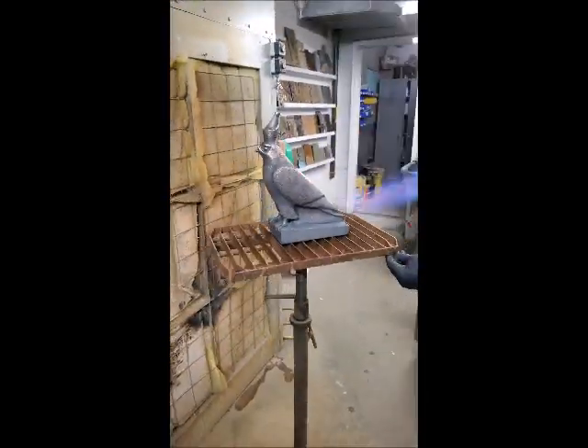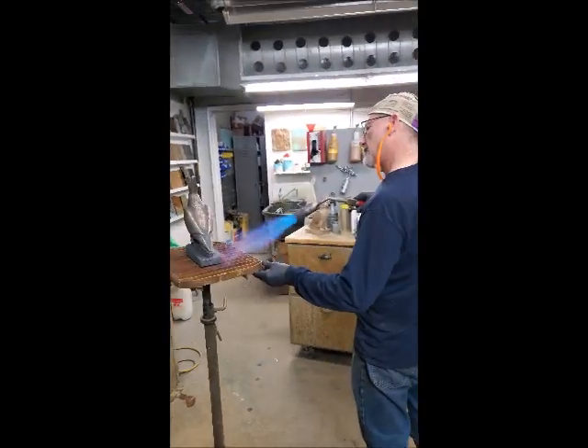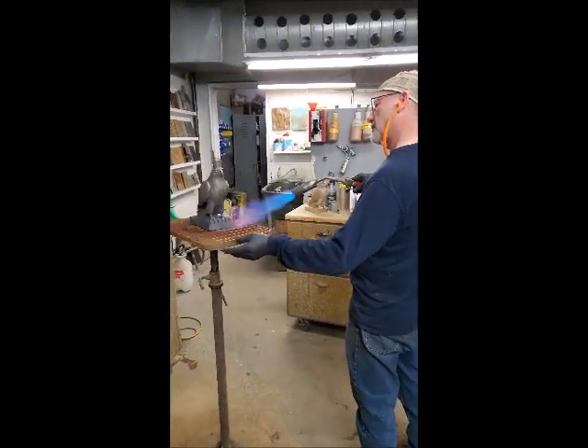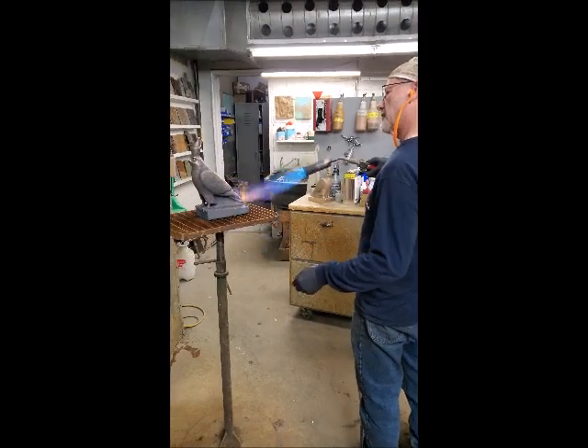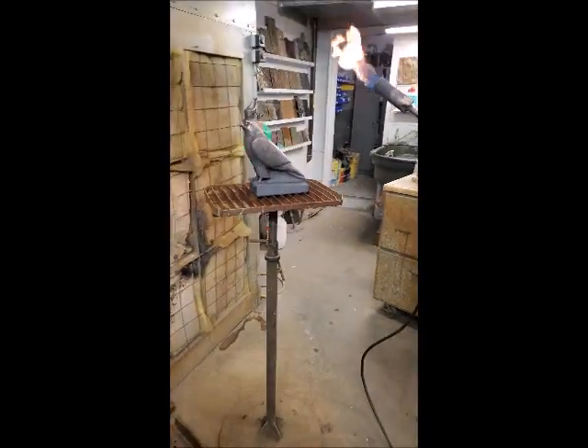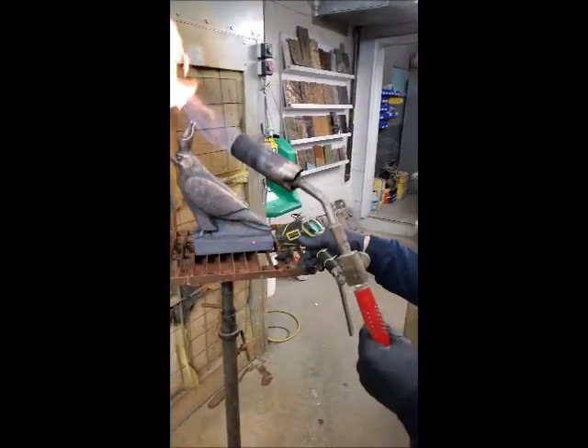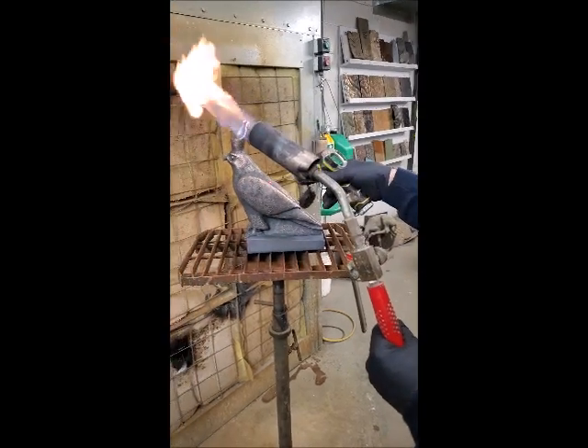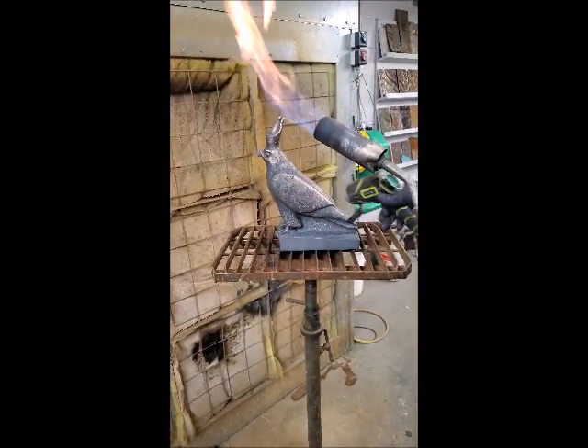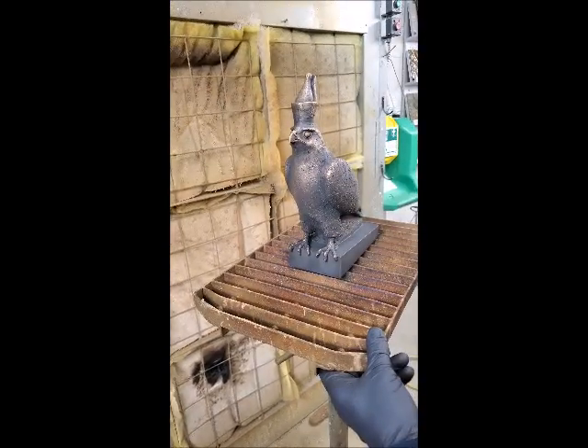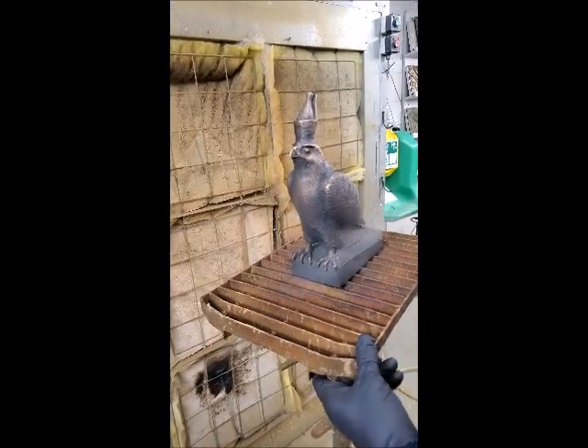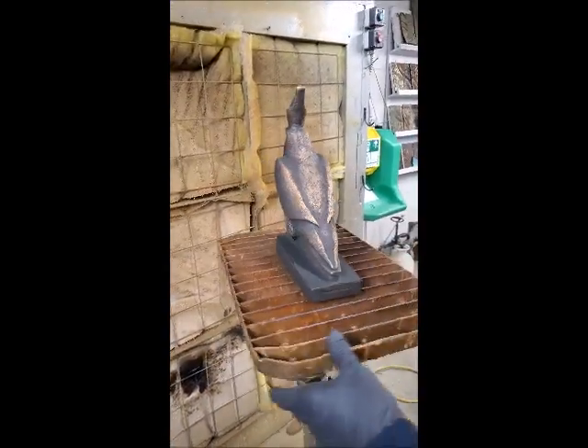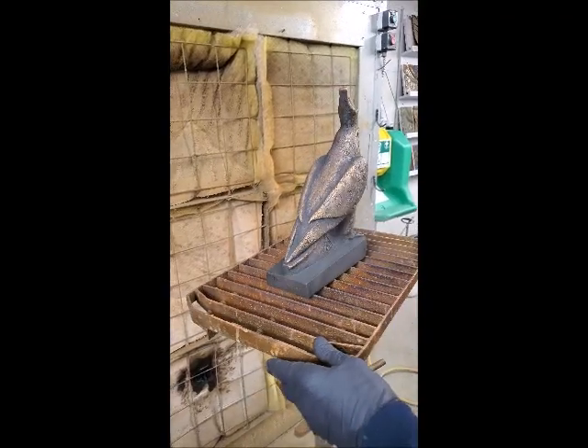The bronze sculpture is then heated to 190 degrees Fahrenheit using a torch, which is the catalyst driving the oxidation of the patina. An infrared temperature gun is used to assure the correct temperature before ferric nitrate liquid is sprayed or painted on to produce the desired colors and tones in the Horus sculpture. Finally, the sculpture is coated with lacquer to protect and preserve the patina colors and tones, and the Horus sculpture is mounted on a granite base.